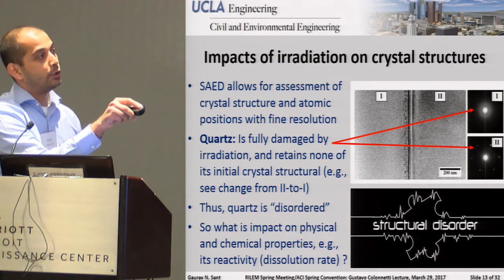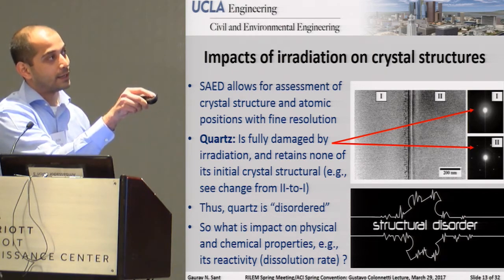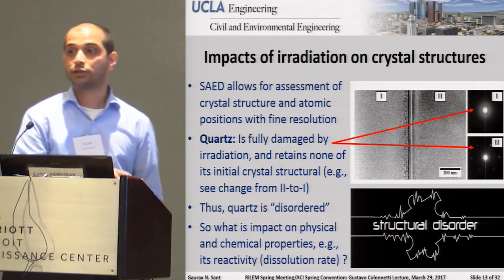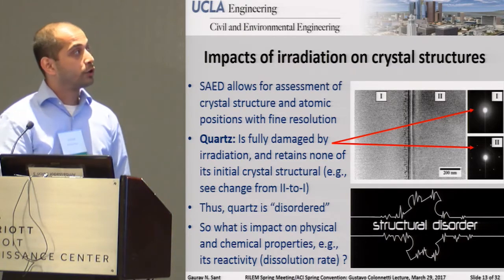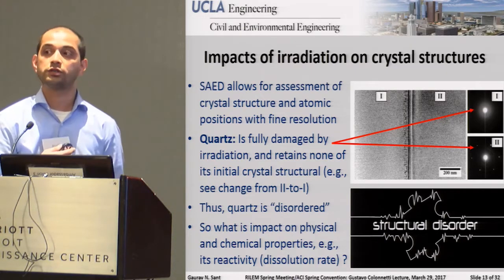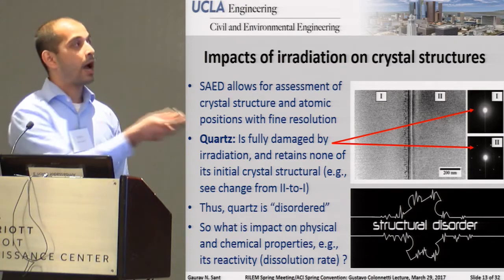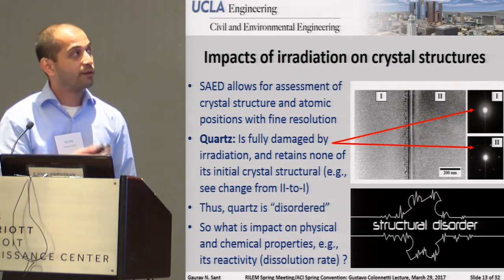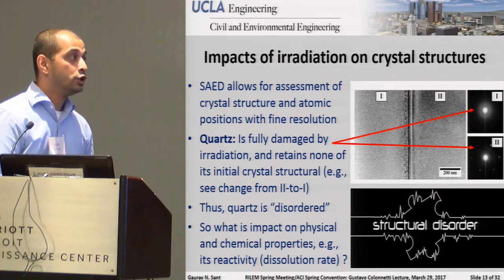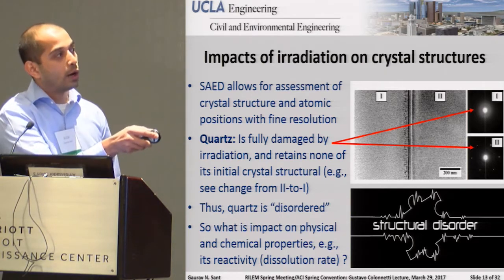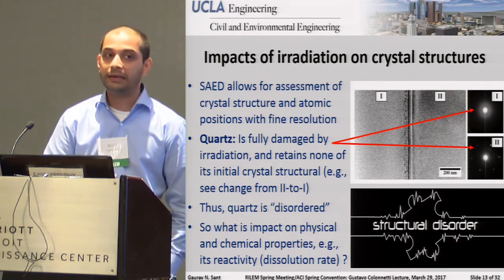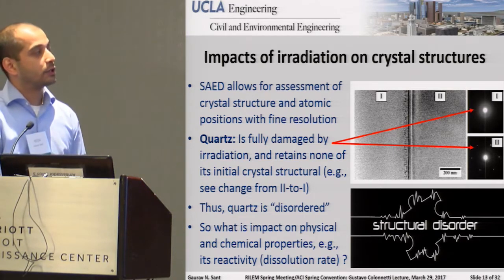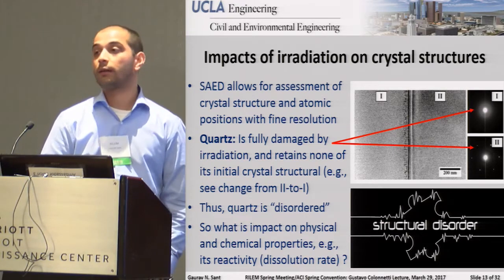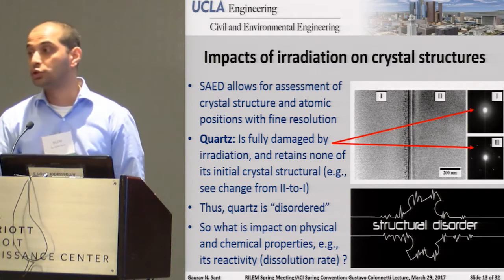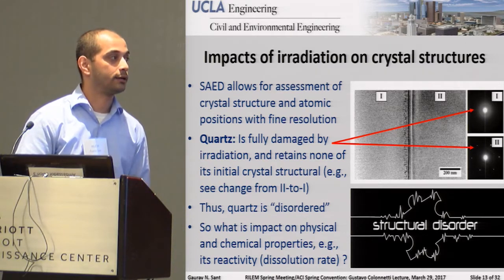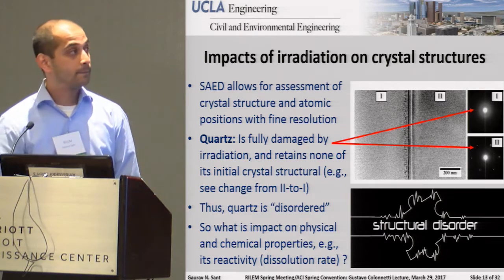If you take quartz and you irradiate it, all of this completely vanishes, and you've got essentially only the central diffraction maxima and nothing else. So what you're really seeing is this example where quartz is being completely amorphized, right? So this is how you would actually examine amorphization at the atomic scale. So since we know that quartz is going from a well-ordered structure to something which is quite a bit disordered now, the first question that comes up is really what is the impact on the physical and chemical properties, for example, the dissolution rate. If we want to probe, for example, something like alkali silica reaction, this is a good thing to be looking at.